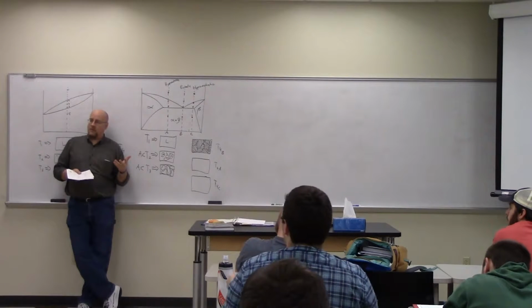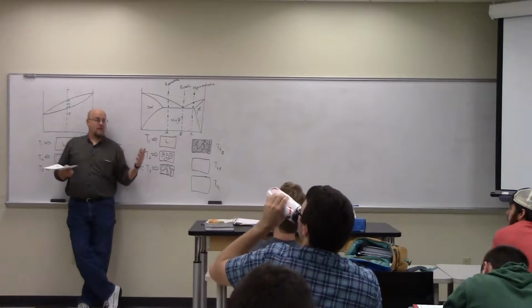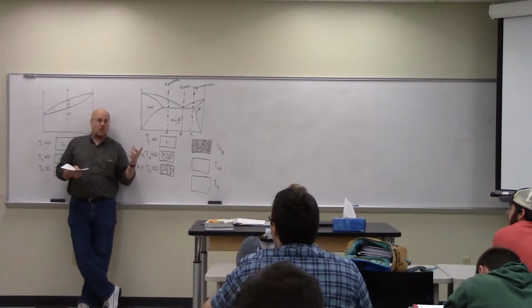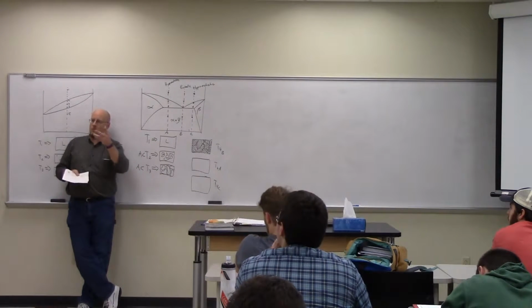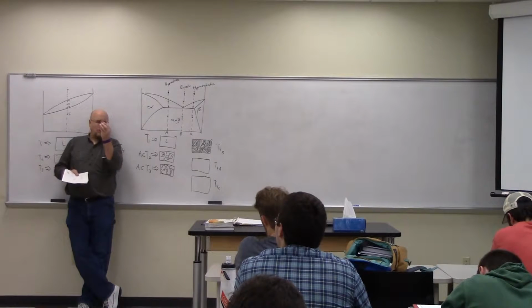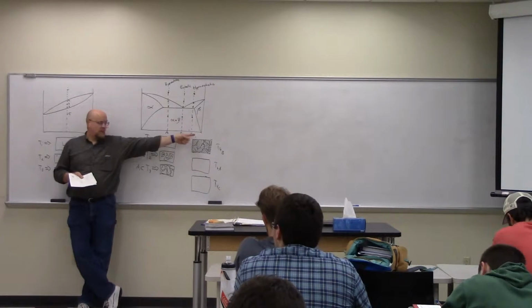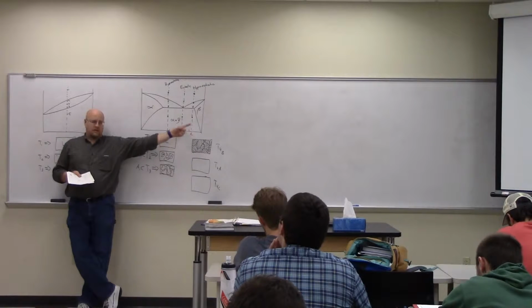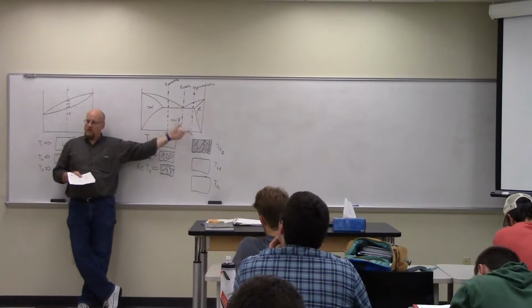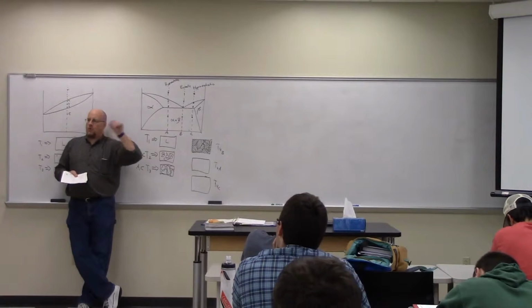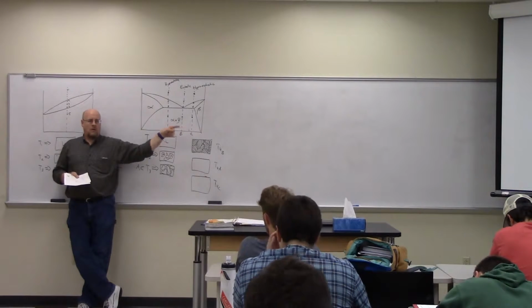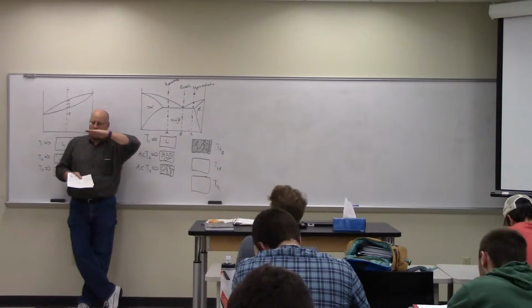Because when the eutectic goes through, it has to suddenly form both alpha and beta. In reality, if it's truly a perfect eutectic, one of them will, because of some spontaneous statistically random variation in concentration, have a few more of whatever the B material is here. Tin in this case. It was lead-tin. There'd be a few tin atoms that might be clumped together, so boom, it would start to form a beta region. So it would solidify as a beta.